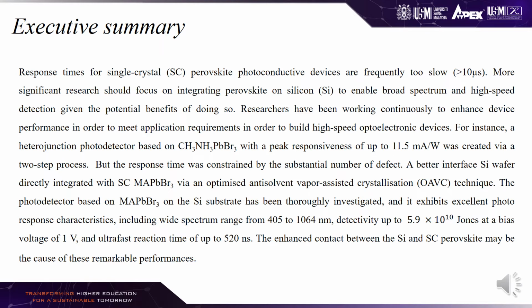For instance, a heterojunction photodetector based on CH3NH3PbBr3 with a peak responsivity of up to 11.5 mA per watt was created via a two-step process. But the response time was constrained by the substantial number of defects. A better interface was achieved with a silicon wafer directly integrated with single crystal MAPbBr3 via an optimized anti-solvent vapor-assisted crystallization (OAVC) technique.